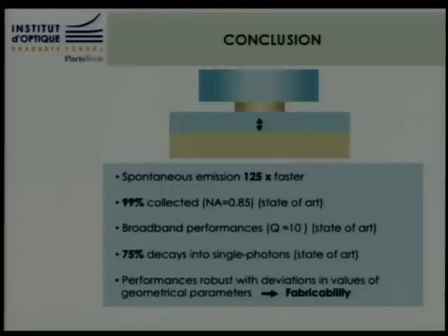It provides broadband performance, and 75% of the emitted power will go into single photons. And all those performances are robust to any deviation of the geometrical parameters, which leads to a possible fabricability.